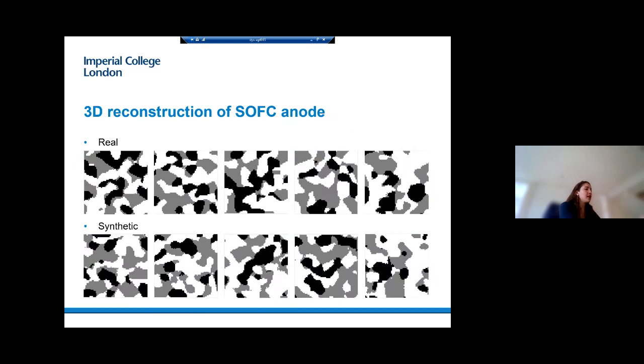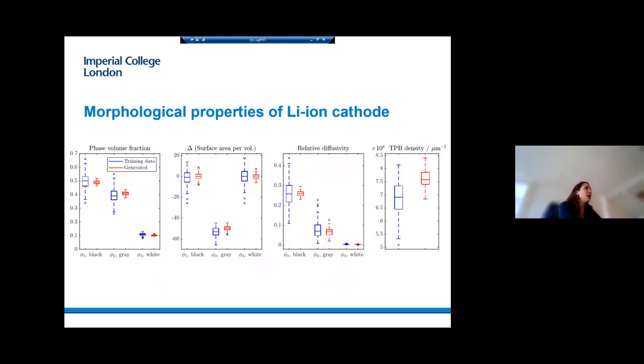So now we can say that we have a generator that with any random sample can generate any synthetic images of the SOFC or of the lithium-ion cathode. Well, because it's not just enough to see whether this is represented visually, we calculated some of the morphological, microstructural properties that usually characterize a microstructure.